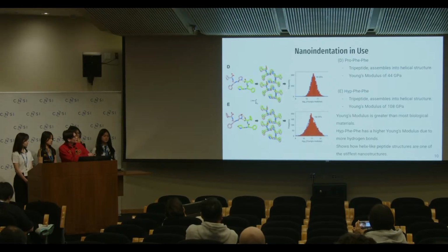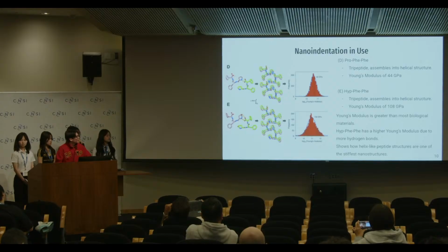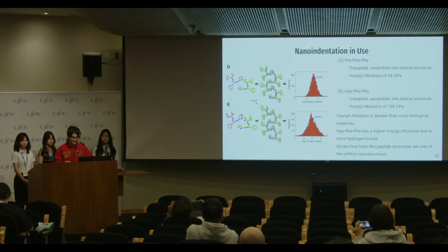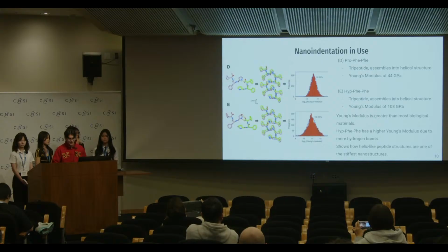And then we also have another one, which is Hyp-Phe-Phe, which is another version of D, but it has a hydroxyl group, so there's more hydrogen bonds. And then after measuring the Young's modulus, it has a Young's modulus of about 108 gigapascals. So you can see how the hydrogen bonding makes the molecule a lot stiffer because it's bonded together more firmly.